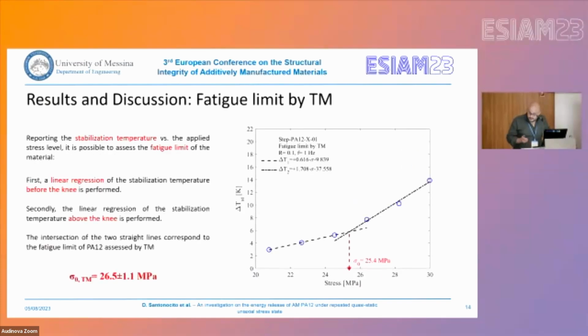We can plot the stabilization temperature versus the stress level, and as we can see, we have a bilinear trend. So we can make the linear regression of these two sets of data and assess the fatigue limit of the material as 25.4 megapascal. So it is in good agreement with the value obtained with the static thermographic method.